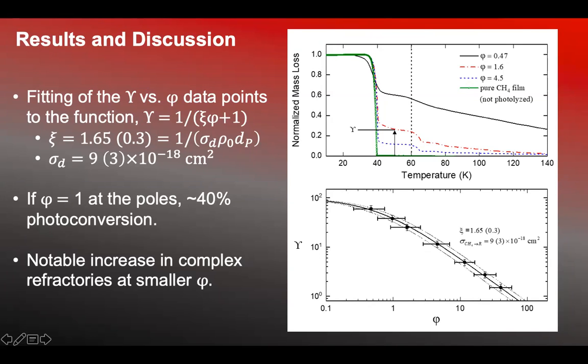So fitting of the yield that we see here versus the phi that's used, we actually get a cross section of that Lyman alpha photolysis process. And again, this is a big question mark that was left in the Grundy paper and the Grundy hypothesis on this deposition of these products at Charon's poles. What is the actual cross section of this photolysis? It appears to be somewhere in the neighborhood of 9 times 10 to the negative 18 centimeters squared. So if phi is equal to 1 at the poles, that equates to a roughly 40% photoconversion of these products here.